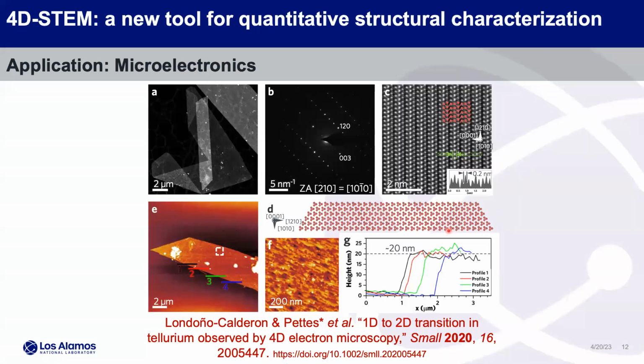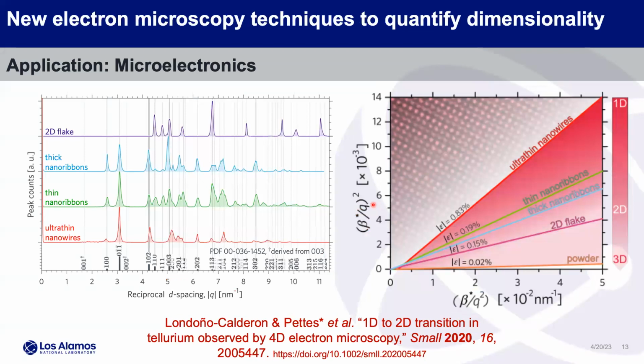We were able to do work on tellurium, which showed that with the 2D material, one, we can get orientation, but also we can see the chiral structure. We see no net chirality. But we're able to make this material in a microwave reactor system. The microwave reactor makes a bunch of different things. It makes 2D flakes, about 20 nanometers thick. It makes nanowires that we measured, and it wasn't just one of them. We measured a lot of them that were down to about 3 nanometers in diameter. And then it makes ribbons, rectangular in cross section, maybe 50 nanometers.